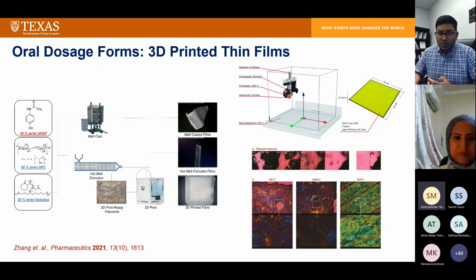As can be seen from this bottom panel, right-hand side, when we did the mapping of the deposited or loaded drugs, we found that for the melt casting, there were some regions where enrichment of the drug was evident. That means some drugs were deposited in an irregular manner. So in some areas, there was more drug, whereas in other areas, the drug was not present in that quantity, which was mainly due to the absence of a mixing process in the melt cast.